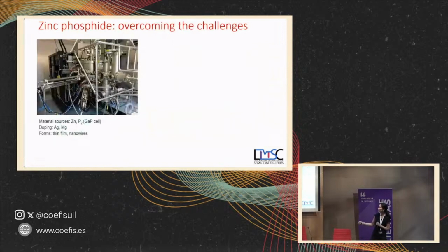Before going into this, here is the machine we use. This is a molecular beam epitaxy system. This is how it looks. It's an ultra-high vacuum. You have the cells below, and we evaporate the materials. We don't evaporate phosphorus directly because it's very dangerous. We evolve the phosphorus from gallium phosphide.